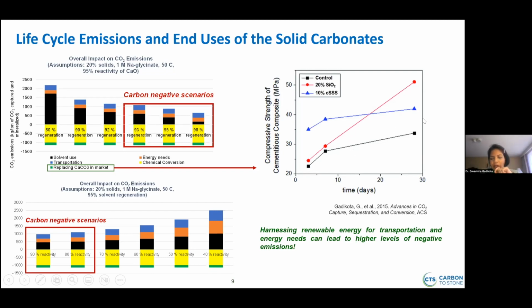So here we have a figure. This is from a very long time ago, from when I was a PhD student. Our team actually showed that if you replace a small quantity of OPC, about 10 to 20% of OPC, with carbonated stainless steel slag, you're able to increase the compressive strength of these materials by a factor of 2. So effectively, our base case is this black line, and replacing that OPC with 10% calcium carbonated stainless steel slag doubles the compressive strength. So this shows that even substituting 10, 15% of OPC with some of these carbonates can actually make for a much more robust built environment. So this is very promising.